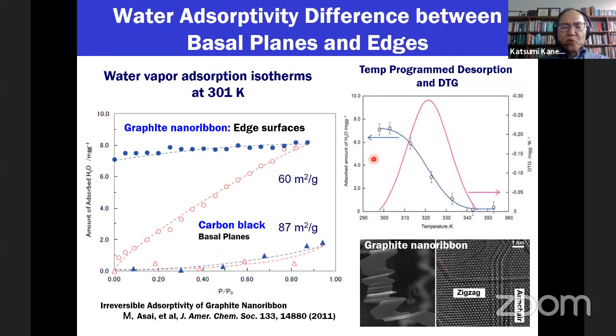Here I want to show some special case. Here I show you some special carbon nanoribbons, which was developed by Mauricio Terrones at Penn State. They have this kind of zigzag form, a very thin form of graphite. There are so many edges. The edge has a very special carbon valence state, and then they should have polar moieties. Then they have a very unique water adsorption behavior.